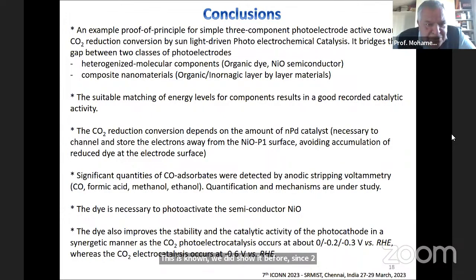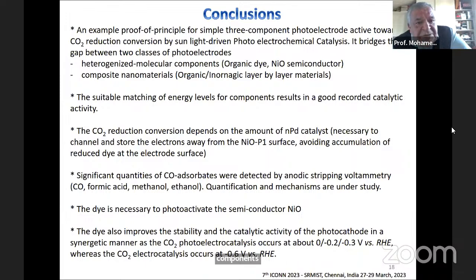And what we did is this composite nanomaterial, where we combine organic and inorganic material, and we make it layer by layer. The suitable matching of the energy level of the components results in a good recorded catalytic activity. And the CO2 reduction conversion depends on the nanoparticle of palladium catalyst, which is necessary to channel and to store the electron away from the NiO-P1 surface and to avoid accumulation of reduced dye at the electrode surface. The palladium really avoids it.